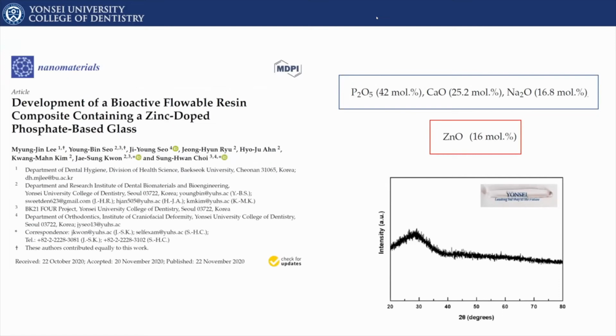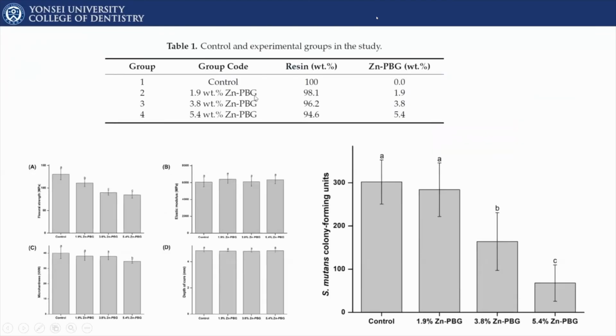So here we wanted to form zinc-doped phosphate-based glasses. On these phosphate-based glasses composed of phosphate, calcium and sodium, we added zinc oxide into the composition of the glasses, and we formed amorphous glasses, as you can see here. The reason we added zinc oxide is to provide antibacterial properties to this flowable resin, and therefore we added these glasses as a filler of this resin matrix in different proportions, as you can see here.